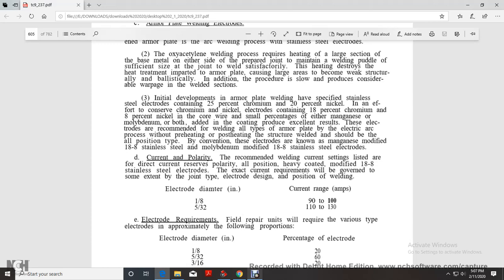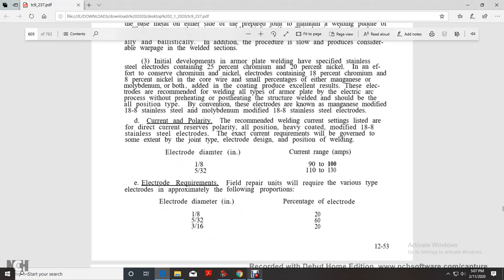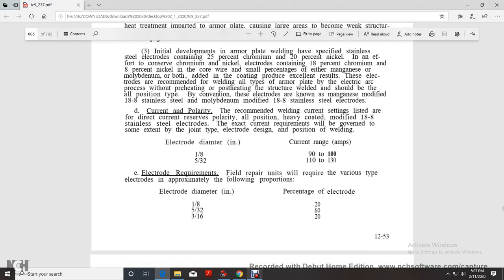The recommended current polarity is direct current reverse polarity for all position, heavy coated, modified 18-8 stainless steel electrodes. Current requirements will be governed to some extent by the joint type, electrode design, and position of the weld. Electrode diameter 1/8 inch, 90 to 100 amps; 5/32 inch, 110 to 130 amps. Electrode requirements: field repair units require various types of electrodes, approximately as follows: 1/8 inch, 20 percent; 5/32 inch, 60 percent; and 3/16 inch, 20 percent.